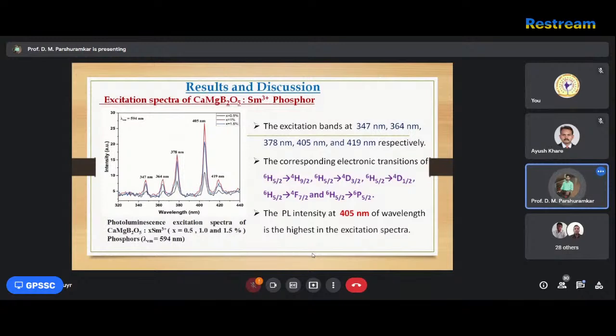Then 364 nanometer excitation is for the 6H5/2 to 4D3/2 transition. The third one, 378 nanometer, is for the 6H5/2 to 4D1/2 electronic transition. Then 405 nanometer excitation is observed for the 6H5/2 to 4F7/2 electronic transition, and the last one, 419, is for the 6H5/2 to 6P5/2 electronic transition. In this excitation spectrum, we see that the PL intensity at 405 nanometer wavelength is the highest, so it is used for the emission analysis.